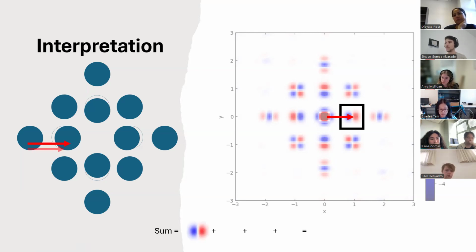One of the pairs of atoms that is a nearest neighbor is that one, right? So what changed as a result of this vacancy in the local structure? What I'm plotting here is the initial vector and then the final vector, so this is before and after the distortion. And what do we see? Okay, we see an expansion of that interatomic distance. Do we agree?